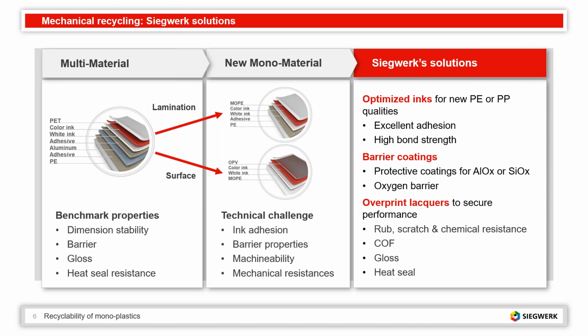And what you will see mostly are challenges related to the surface properties of the new film structures, because this is what you change. You change the film on the surface, and all of a sudden you have different rub and scratch resistance, in particular when you go to surface print from lamination. This can be a big challenge. Your COF, your gloss, everything is different, and in order to correct that and to get you back into a manageable area, we at Siegwerk have developed a whole range of overprint lacquers. And these overprint lacquers can secure the performance of these monomaterial structures so that you can actually replace the multi-material structures with that.